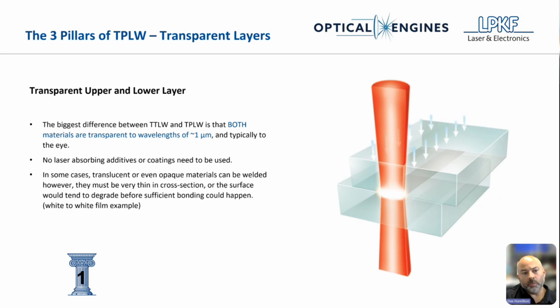So diving into this a little bit more, transparent upper and lower layer. The biggest difference is that both of these materials are transparent to the wavelengths of 1 micron and typically to the eye. No laser absorbing additives or coatings needed or can be used. And in some cases, like I said, translucent or even opaque materials can be welded, but they need to be very thin. So going back to when I mentioned nylon, being that it's in its natural state somewhat milky, that just needs to be a very, very thin layer for the top to be able to get the laser energy through without burning or adversely heating up and thermal expansion happening and melting.